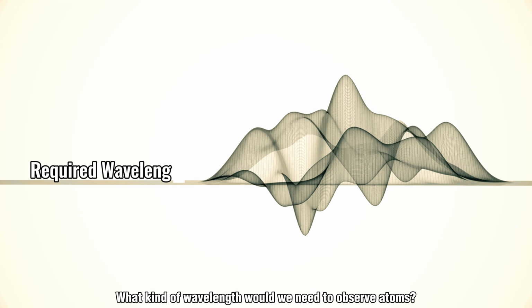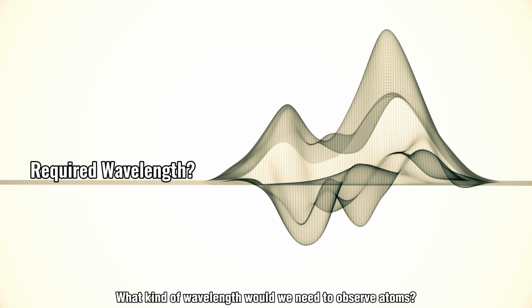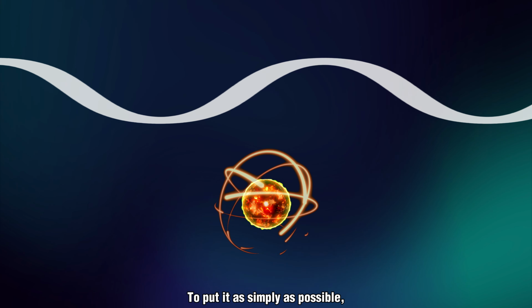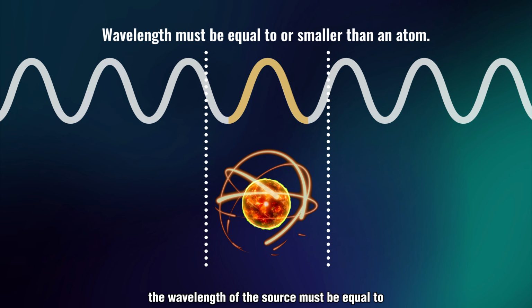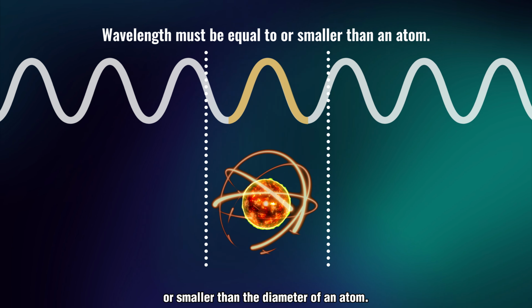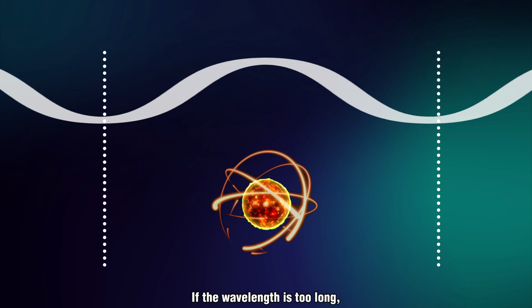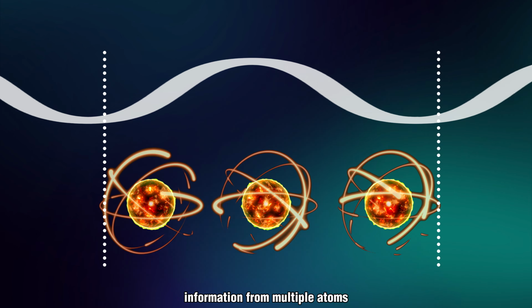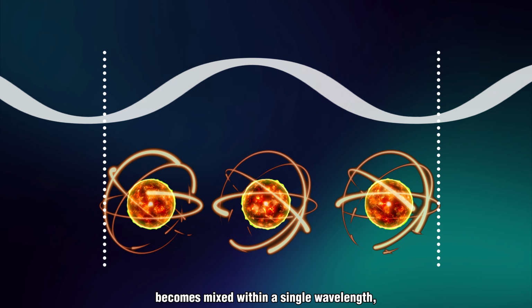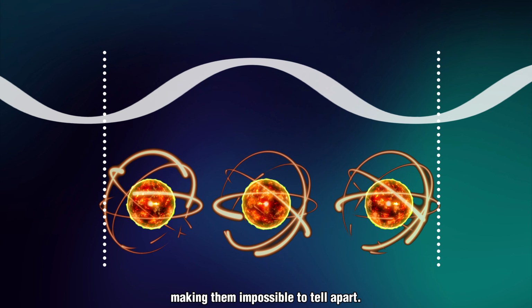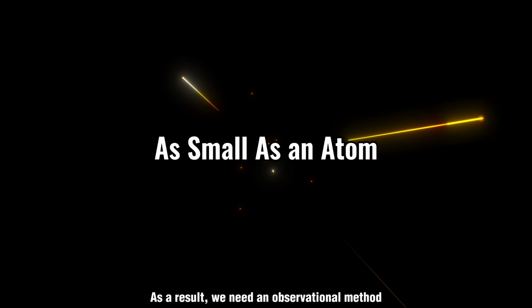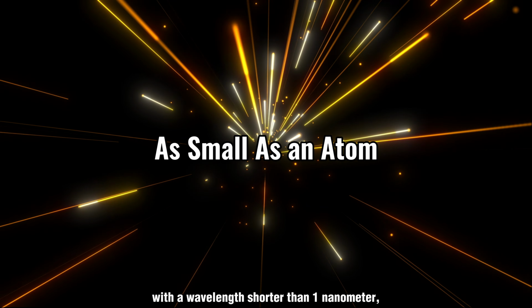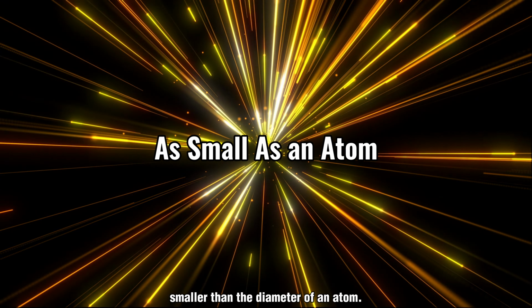So, what kind of wavelength would we need to observe atoms? To put it as simply as possible, the wavelength of the source must be equal to or smaller than the diameter of an atom. If the wavelength is too long, information from multiple atoms becomes mixed within a single wavelength, making them impossible to tell apart. As a result, we need an observational method with a wavelength shorter than 1 nanometer, smaller than the diameter of an atom.